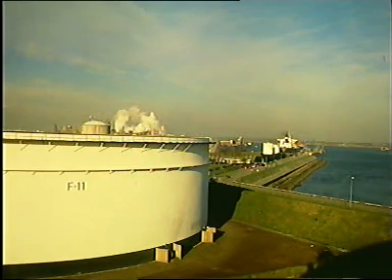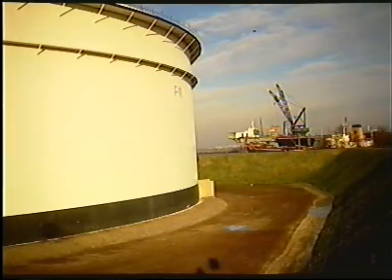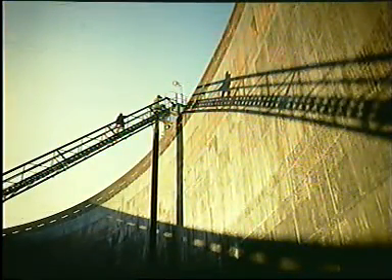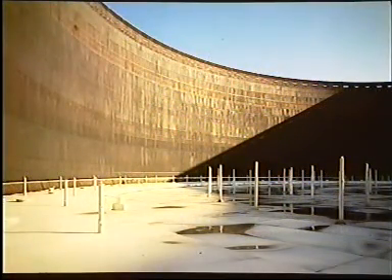Over the years, a strange situation has developed. Coating tank externals was quite normal, but the interiors were rarely lined, except when essential to keep the contents free of contamination, or if the cargo was highly corrosive. Experience showed that pitting and even perforation occurred in not obviously corrosive liquids, such as heavy fuel oils or crude oil, particularly when these products were contaminated with water and acids. Extra steel thickness added as corrosion allowance did not help much in the case of pitting corrosion.